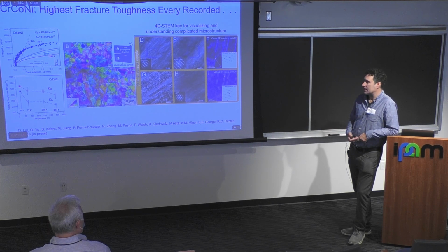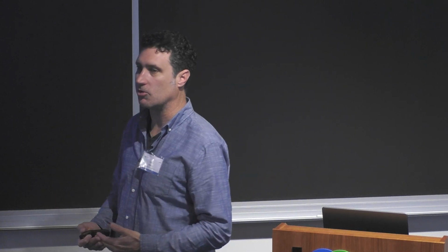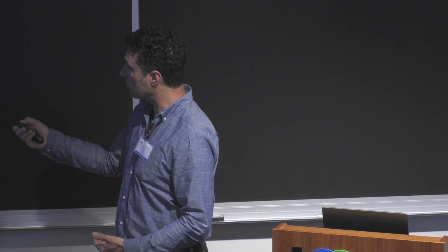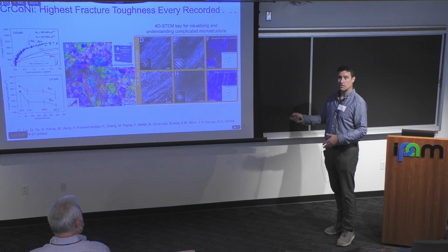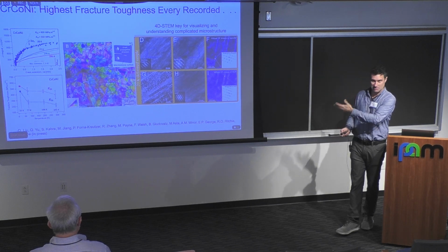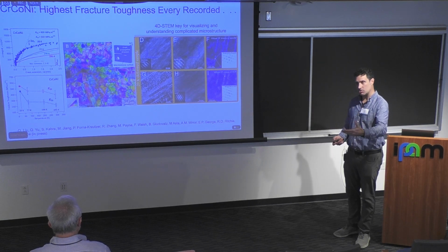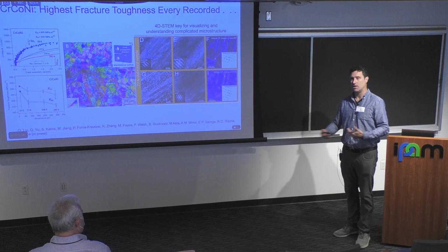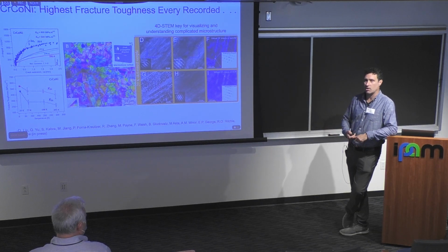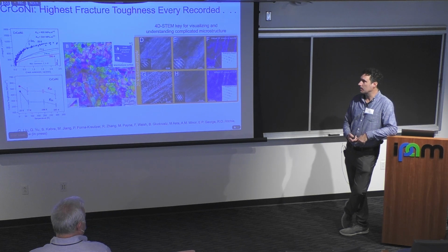Another thing that's interesting about this alloy, it's not unique to high entropy alloys, but a lot of materials get brittle at low temperature, right? You think of the ductile to brittle transformation temperature, a lot of materials get brittle. Materials that twin, like HCP materials and like FCC that's bordering on HCP like this, tend to actually increase their toughness, increase their strength at low temperature, because twinning is a really excellent hardening feature.